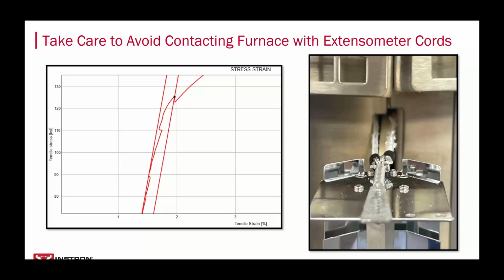This might not be as noticeable in small strains observed in the elastic region, but once the specimen starts to yield, the problem will become quite clear, as you can see in this zoomed in stress strain plot on the left. If you're not familiar with this type of challenge, this can be difficult to actually observe because the interference is so slight. But now that you know this, you can very easily modify the furnace to adapt to the extensometer,